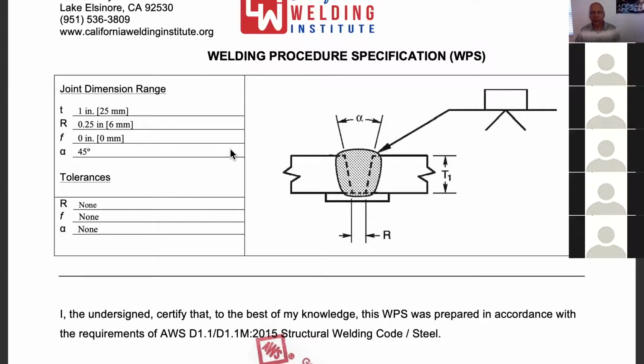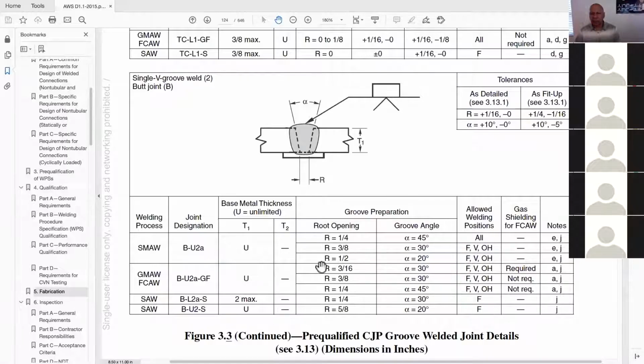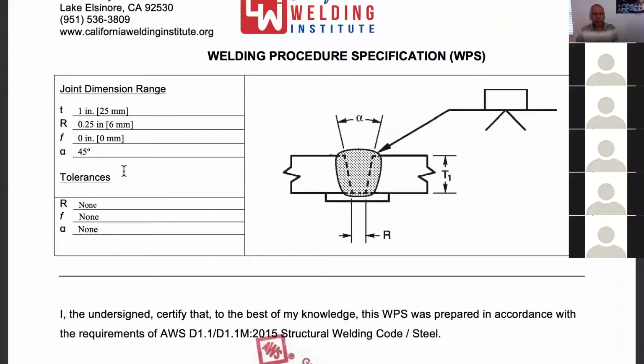as add the 1/16 of an inch that is given to the detailer, right? So instead of that 0.25, I would go 1/4 inch plus 1/16. That would give me a 5/16 root opening. And then I would add the 1/4 inch and plus or minus the 1/16 fit-up tolerances. I could detail it as I wish with that 1/16 tolerance that is allowed for me to use. And then the fit-up tolerances here would be plus 1/4 and minus 1/16 and so on. In the case of a weld test coupon, we go, nope, no sir, you're not allowed any tolerances because Clause 4 has a joint sketch and it does not allow you to deviate.